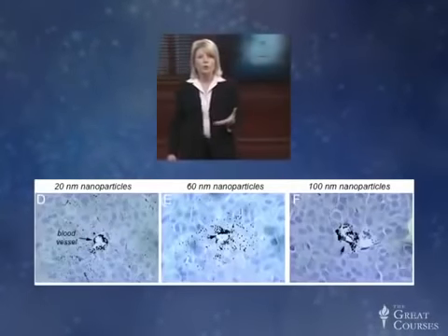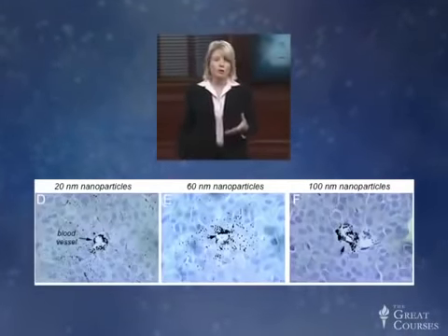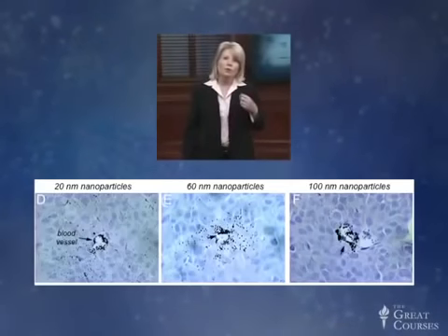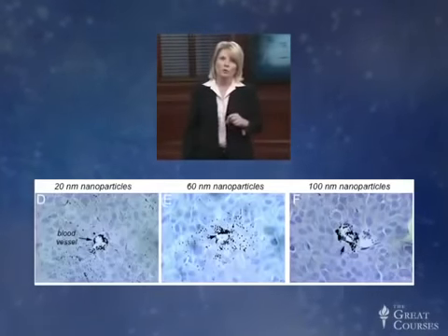to over 100 nanometers. A recent study compared 20 nanometer and 100 nanometer particles that were introduced into a mouse that carried a tumor. The animals were examined after different time intervals, and then portions of their tumors were analyzed. So as we look at gold nanoparticles that can selectively eliminate cells, we have to keep an eye on the sizes of the particles. Smaller seems to be better to enable the particles to travel away from a blood vessel and penetrate a tumor. This makes sense, as the particles need to be able to slip in between the cells that make up a blood vessel.